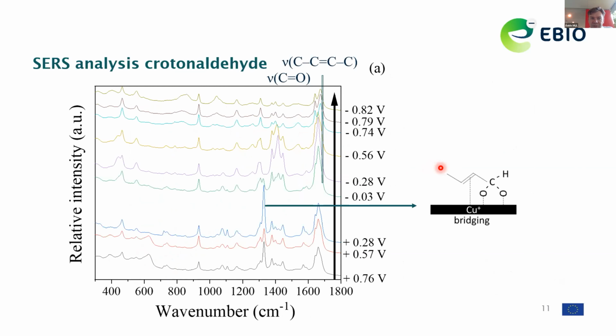Now, this is completely different if we look at the double bonded version of the molecule. And again, I won't go into detail of all the Raman bands and what they exactly mean. But here we have, again, a very strong intensity peak at about this region of 1300 to 1400, which we can assign again to a similar structure, a carboxylate structure, but now of the double bonded version of the crotonaldehyde on the oxidized copper surface. And again, if we go to more negative potentials, we remove this peak. You see this disappear in the spectra here. And what is left is sort of an intermediate stage here with some new features.